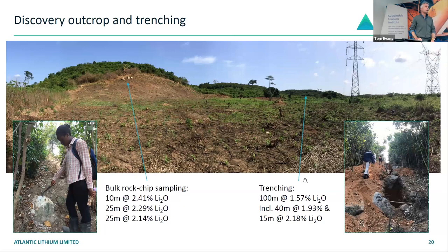It's highly weathered. And sampling of lithium pegmatites at that time was a bit of a struggle. Labs hadn't really got it down packed in terms of their calibrations. So we had lab issues. We didn't really know what we were sampling. We could see there were white felsic rocks, but we didn't know what spodumene looked like, and especially when it's weathered. And then also the samples we initially collected were weathered, and they all came back at around 0.1, 0.2, not the 1 or 2% we were expecting from those geological survey reports.